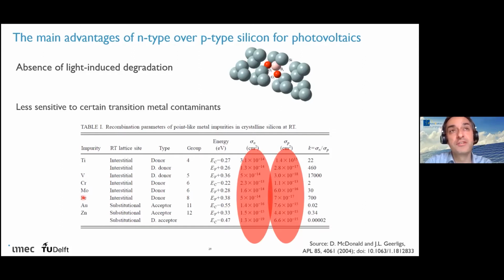So the higher the efficiency, the more sensitive you are to impurities. We have to consider that we have large factories now producing many gigawatts per year, and you will always have some contamination - it's unavoidable. People have to take care to avoid contamination as much as possible, but we also have to look for processes, cell structures, and wafer types that are least sensitive to the contamination we're anyway going to have if we want to reach high efficiencies. That's the main reason people are switching to N-type wafers in high efficiency concepts.